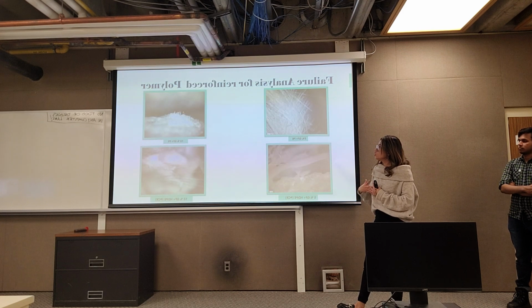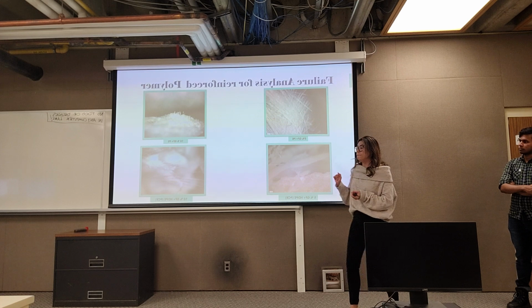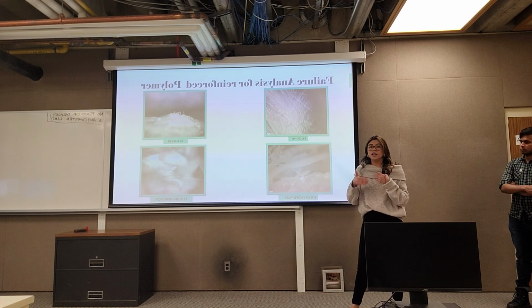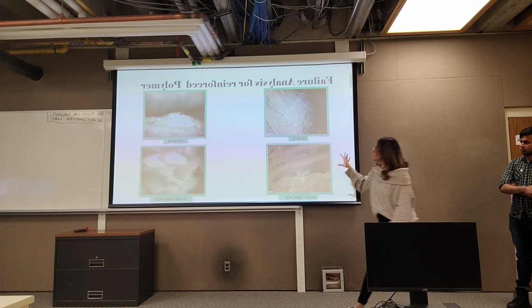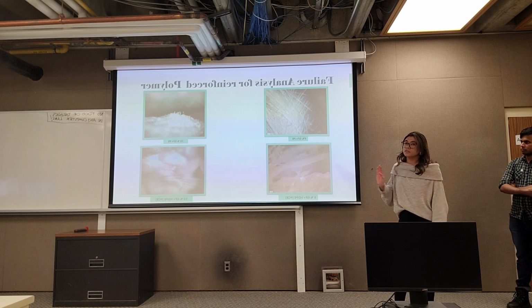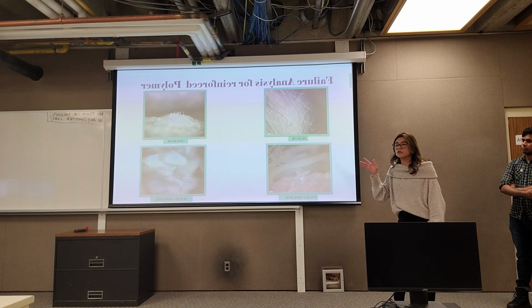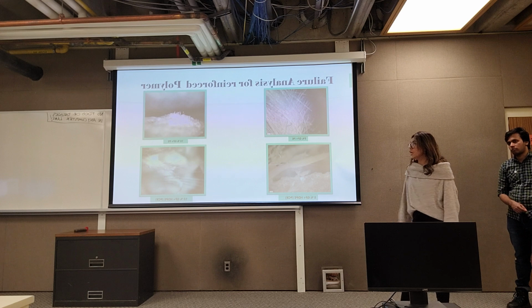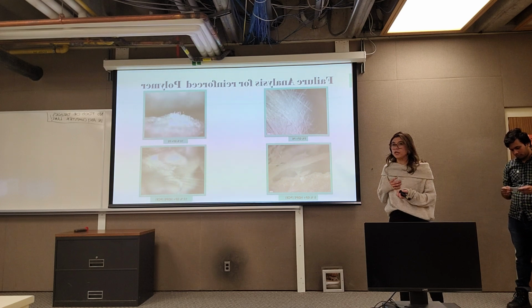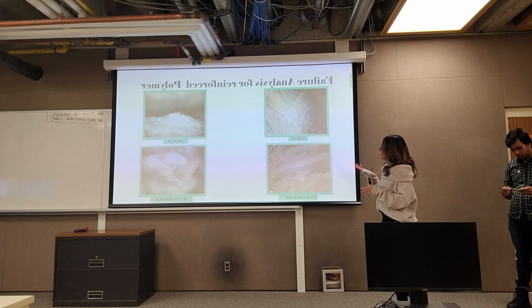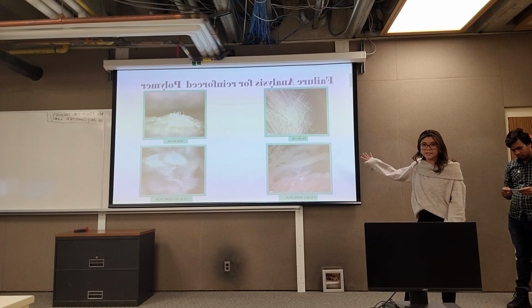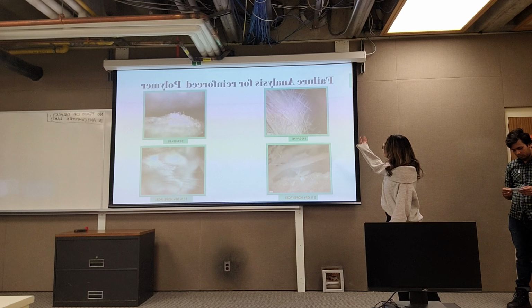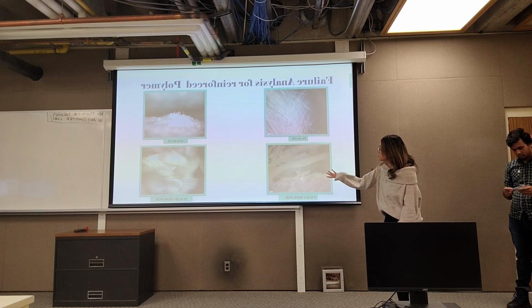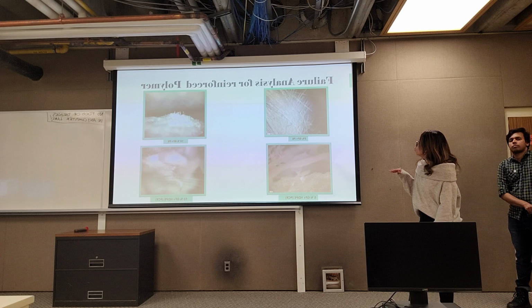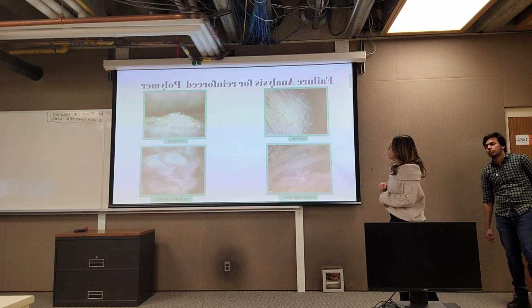After this, we reviewed the failure between the reinforcement and the matrix. So we analyzed some samples that were created with the two-step process, the compression and the injection. And we found out that the primary cause of the failure was the fiber pull-out. We could see, as in these images, that most of the glass fiber was pulling out of the matrix.